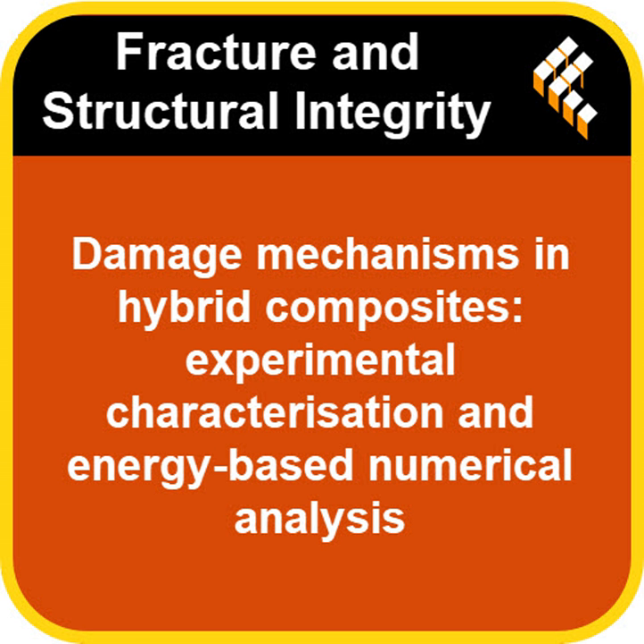How so? When glass was on the compression side, the friction energy between the layers tended to increase steadily as they bent it more, right up until the end of the test. Okay. However, when the glass was on the tension side, they saw a sudden drop in friction energy after the peak force. Their theory is that this could be because the layers were starting to pull apart or fail significantly, reducing the contact area and therefore the friction between them. Ah, that makes sense. Less contact, less friction.